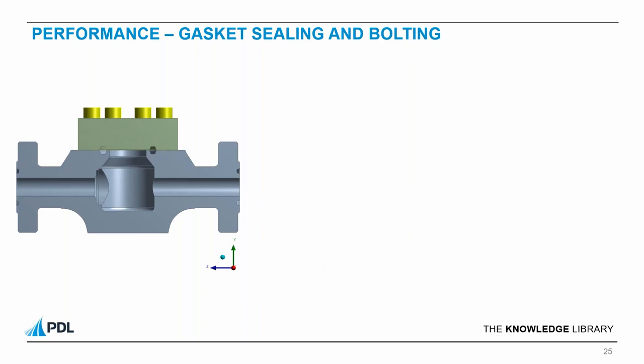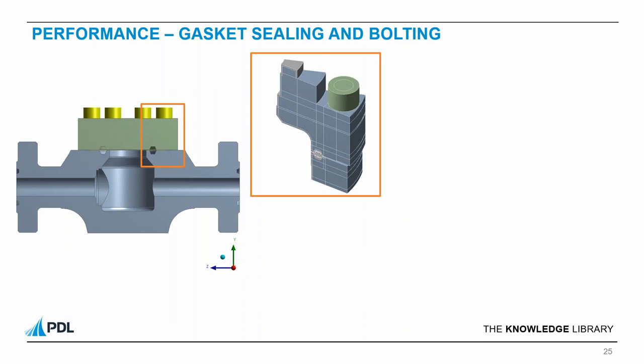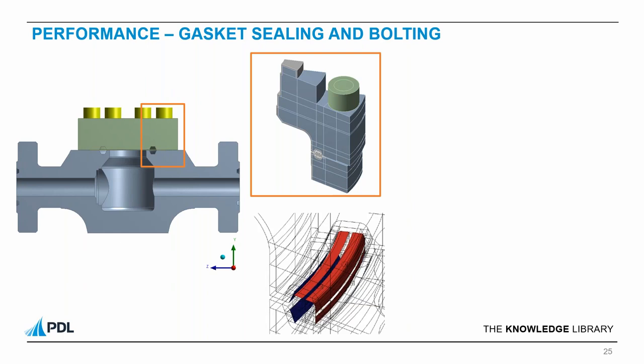If we wanted to verify the sealing of the gasket and ensure the bolt preload is adequate, we could create a cyclic symmetry model as shown here. A submodel is a quick way because it's quick to set up and solve. And for assessments where components are constrained only by contact, in this case, the gasket, it can help convergence. Until contact is established between the gasket and its seal groove, it is essentially floating. So it can help to apply the bolt load as a displacement, then swap it to a preloaded force. This is typically helpful if the gasket is elastic plastic and the material is deforming.